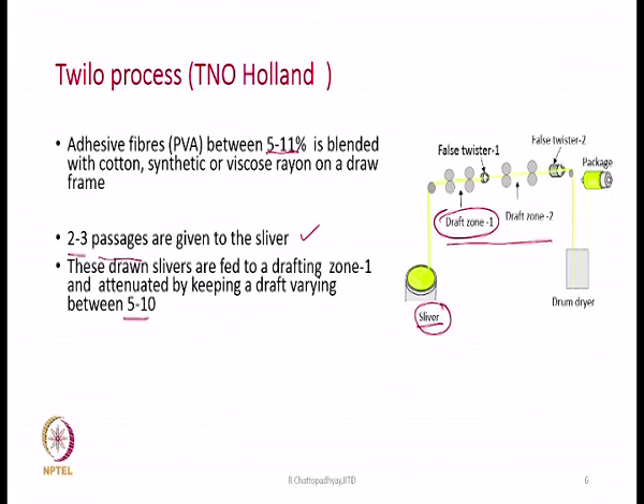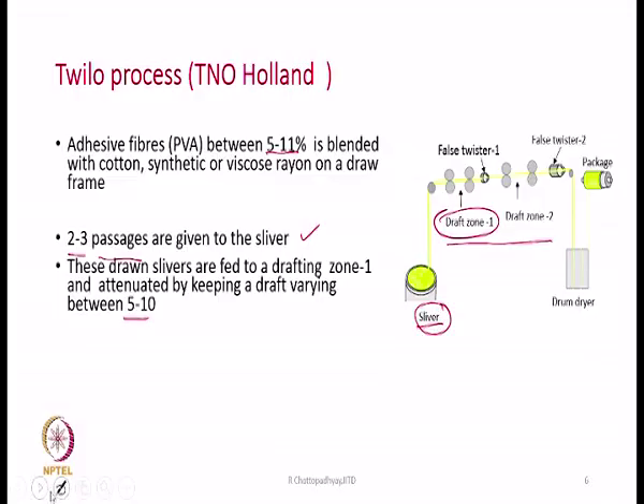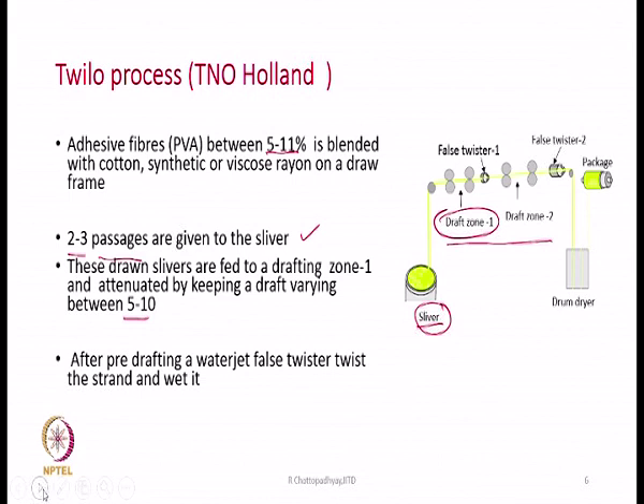Some attenuation happens to the sliver, so the sliver becomes 5 times or 10 times thinner. That is called the pre-drafting zone or pre-draft. So, we have given this much amount of draft, but this much draft obviously is not sufficient to make a yarn. From sliver to yarn, the total requirement of draft is of the order of 200, 300 in this range, depending upon what is the count of yarn you want to produce.